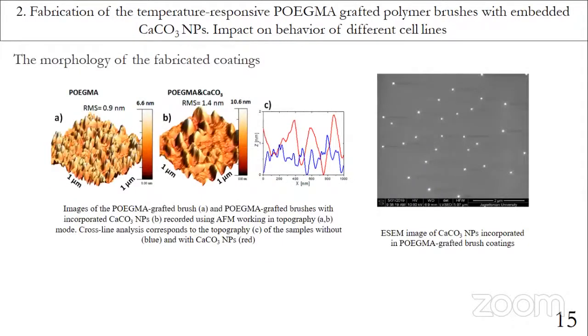This is AFM data and the SEM photo. The SEM images recorded for samples with calcium carbonate nanoparticles incorporated in polymer grafted brush coatings demonstrate uniformly distributed calcium carbonate nanoparticles, the square shape. Their size did not exceed several tens of nanometers.